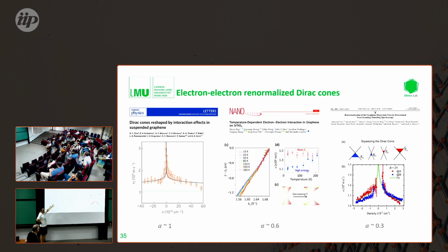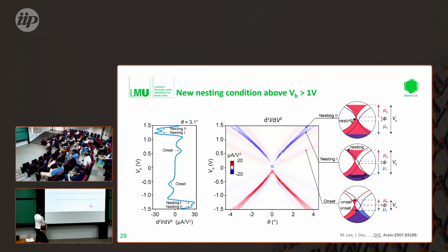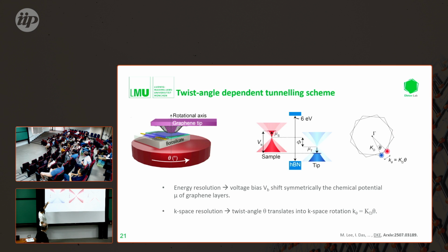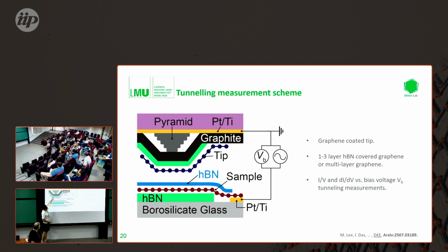And then there's more literature, maybe you can find 15 experimental papers or so. I would say also that here the effect is a little bit overestimated. If I compare to the later follow-up work, the effect was usually 10 to 20%. Here you see that it's almost like 300%. Maybe if you suspend a device, strain also matters. And yes, it's both sides: hBN here, the green one, and here.